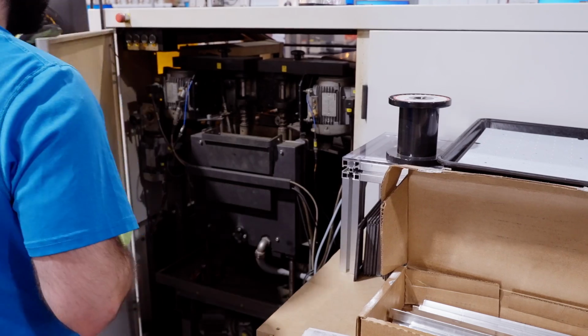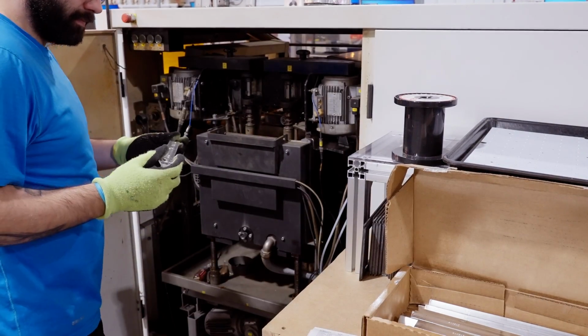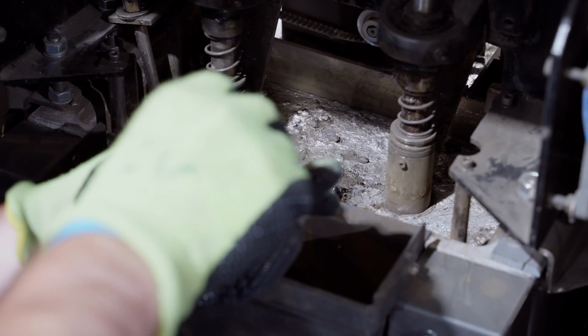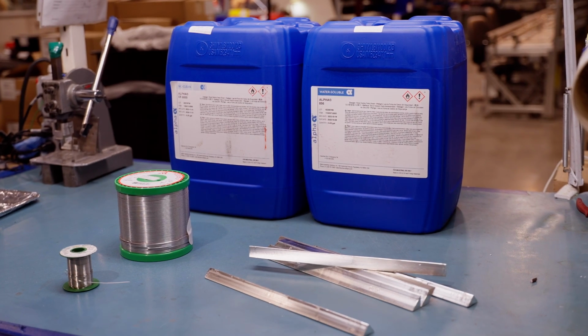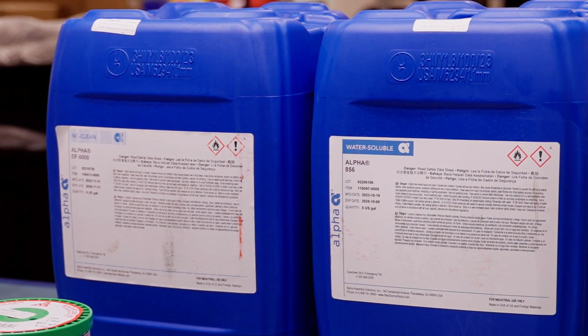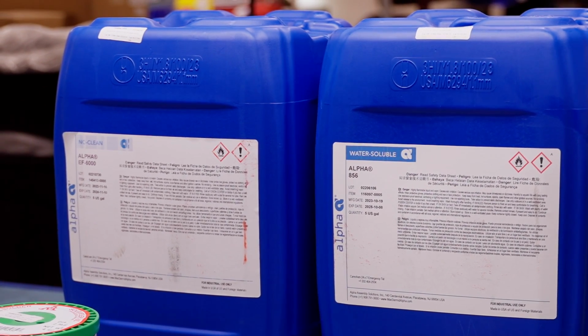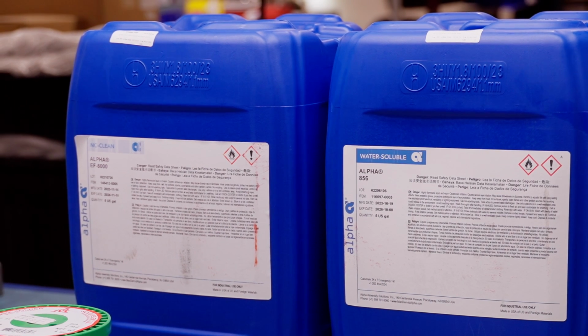Bar solder uses wave soldering instead. Solid bars are loaded into a heated wave solder pot. The flux is separate and sprayed onto the boards. There are two types of flux, no clean and water wash. Both come in gallon jugs and are about 90% alcohol.